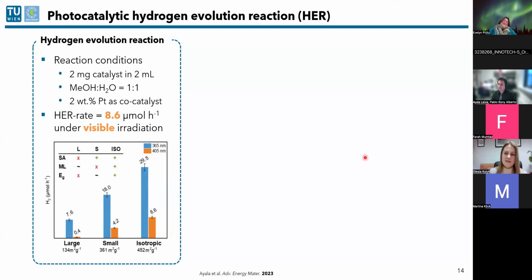And one more question. Can we combine one titanium MOF with a different titanium MOF or other MOF to make a heterojunction with improved activity or even stability? Yes, that's ultimately the goal, I would say. If you find, for example, a MOF that is very good at the oxygen evolution reaction, and another one that is very good at the hydrogen evolution reaction, and you have optimized both separately, you could, of course, make a heterojunction. The question is how to have them with a good interface. But I think MOFs can be surface functionalized, and MOFs would be a great platform to investigate heterojunctions as well.